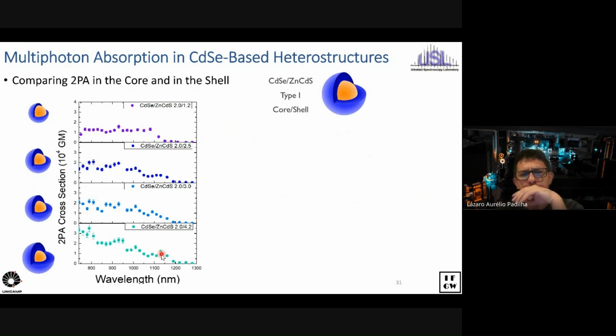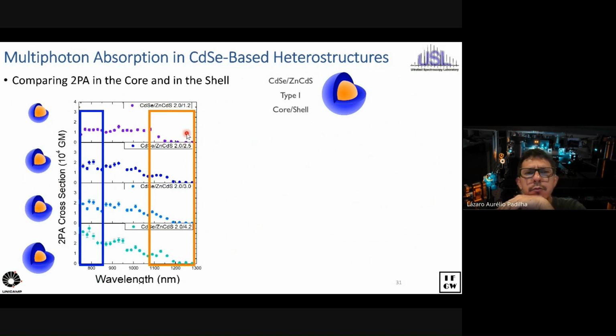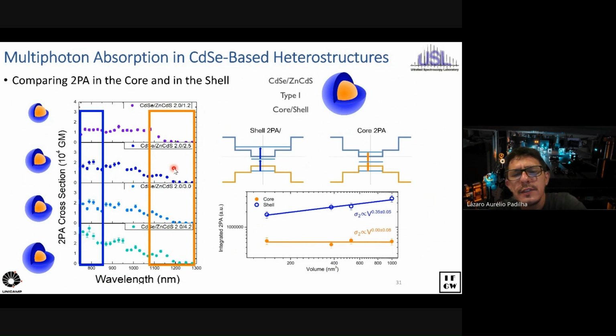So if we look at the spectra, and if we take this region here, the orange region, at this energy here, the absorption from the shell didn't kick in yet. And if I take this region here where the absorption from the shell kicked in and compare how it depends on the total size, one would expect that this would not change with the size because the absorption from the shell is not here yet. And in fact, that's what we see. In this orange region, it's basically independent of the volume. Now, for the blue region, we have volume to the 0.3.